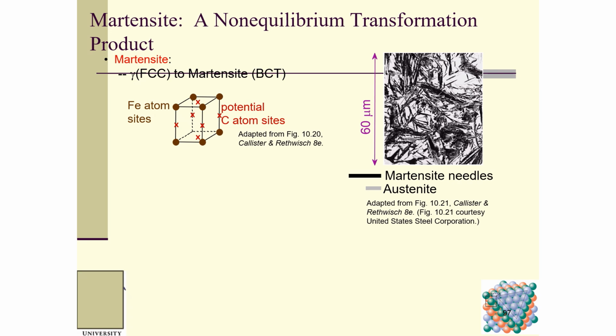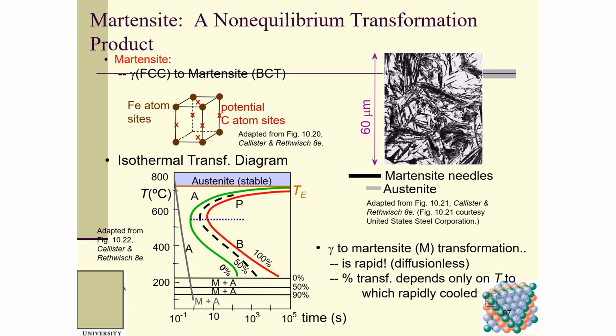Then we'll talk about martensite. Martensite is very, very important. It is a non-equilibrium transformation product, and you can see it looks like needles. Martensite goes from FCC to BCT. The crystal structure changes. On the isothermal transformation diagram, when can we get martensite? When the system has a very, very high cooling rate, one that does not intersect these two curves. Then we can get martensite. Martensite forms very rapidly and is diffusionless because the time is very short. The percentage of transformation depends on the final temperature to which it is rapidly cooled.